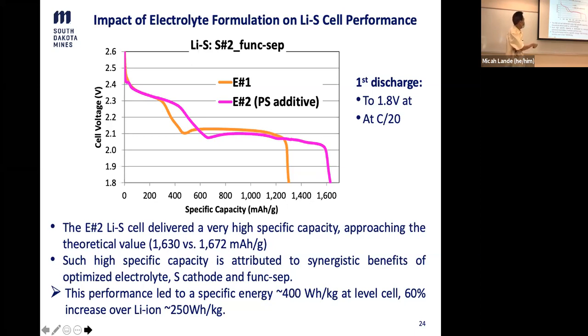If you look at the end of this chart, the capacity delivered is actually pretty close to the theoretical. That's very amazing. For sulfur chemistry, if you search the literature, there are not many results showing close to the theoretical value. They are in the 1,000 or 1,200 range. So this is pretty amazing that just by electrolyte work, we can achieve this type of advantage.